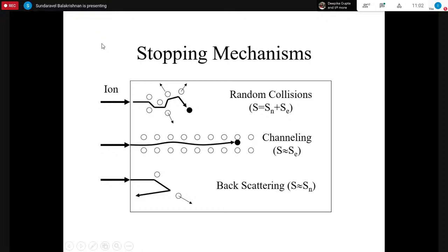then we can tell the crystal quality is good. And if you look at what sort of stopping mechanisms are there, in normal Rutherford scattering there are random collisions, and in energy loss there are both nuclear as well as electronic contributions. And in channeling, there are only small angle collisions. The nuclear energy loss is negligible, and it is dominated by the electronic energy loss.